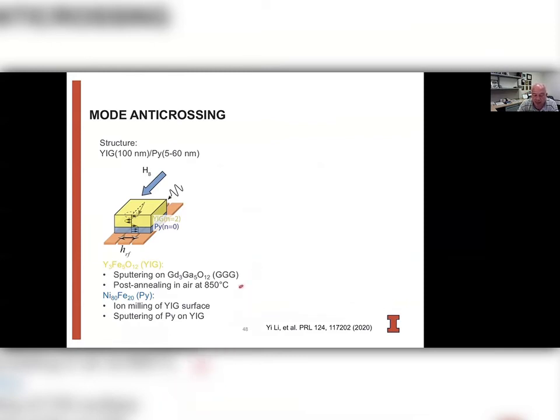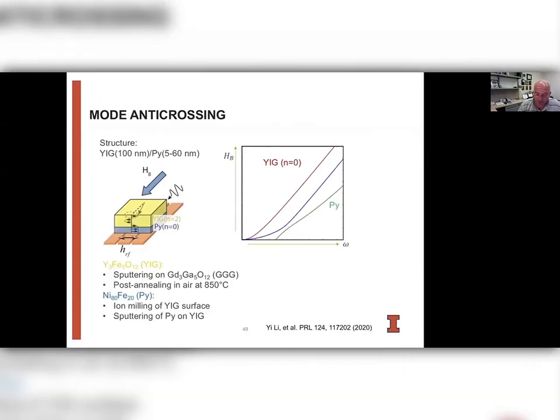We post-anneal the structure to get highly crystalline yttrium iron garnet. And then before depositing permalloy, we clean the surface a little bit with ion milling, and then add a permalloy structure via sputtering on top of the yttrium iron garnet. And so the goal is then to have a situation like this, where the spin wave mode crosses over with the Kittel mode of the permalloy, so that we get some hybridization gapping here.